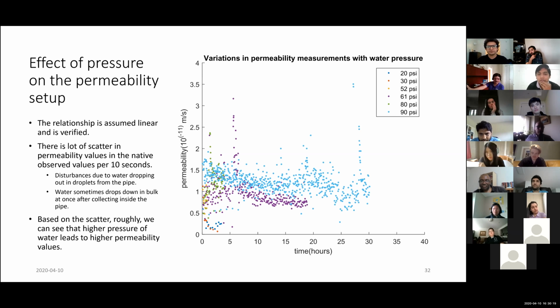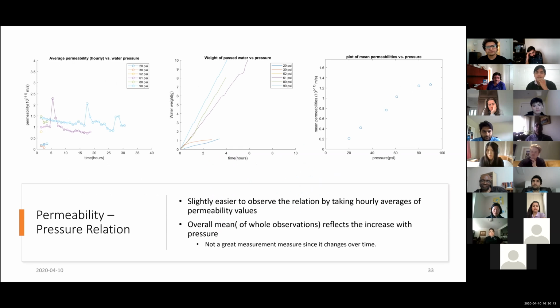So this plot is okay. I'm not as bothered by variability in these tests as I normally would be in a permeability test, where you see huge variability in data. One order of magnitude is very common, even in the same test, even in the same pressure range. So not seeing that here, I'm kind of comfortable with that. So maybe that equilibrium test, which you're not running, probably is one of the reasons. And second is maybe pore blocking.